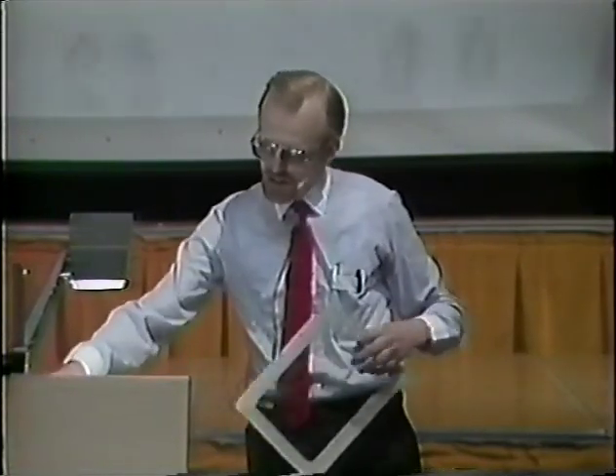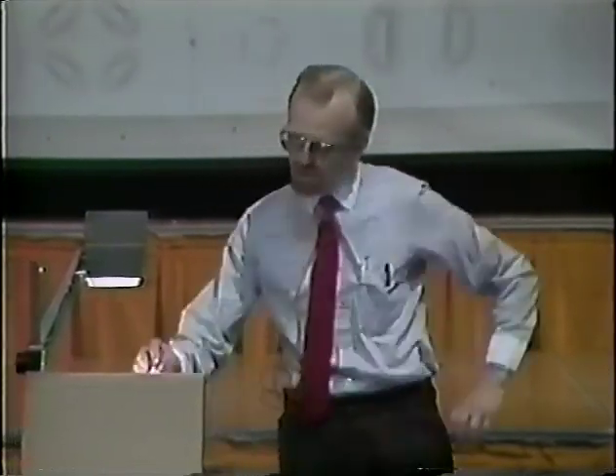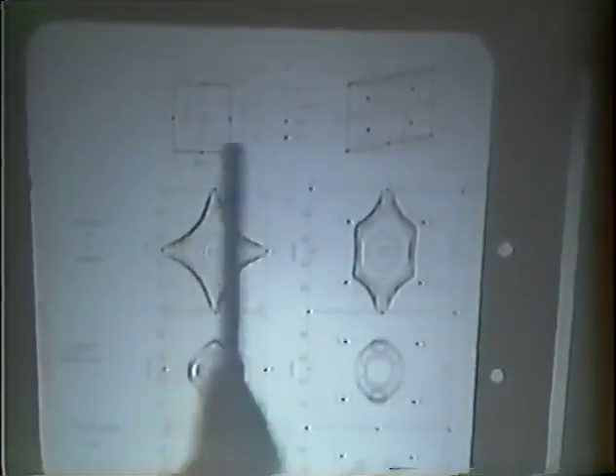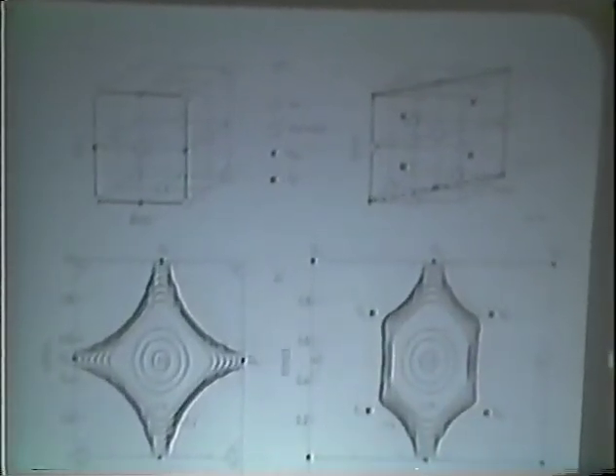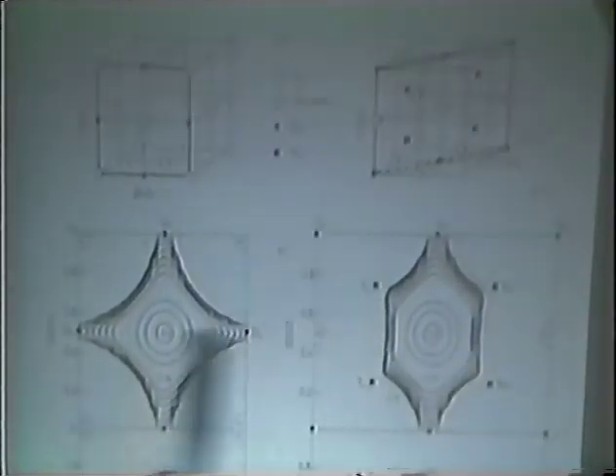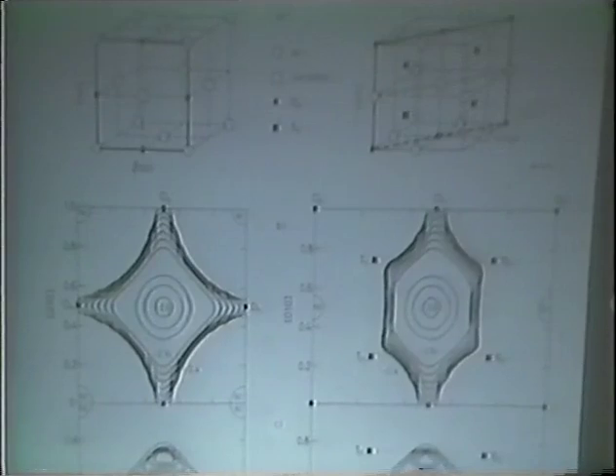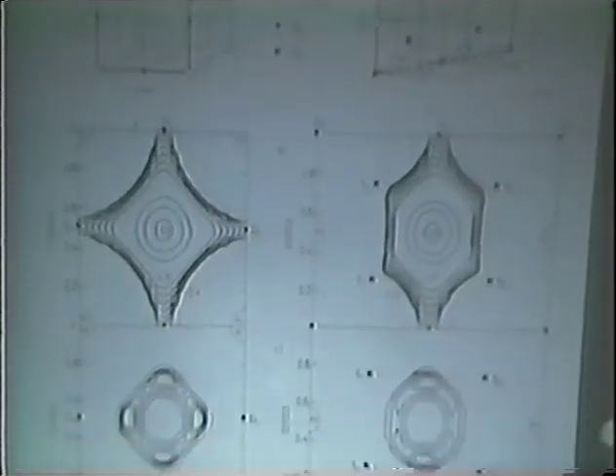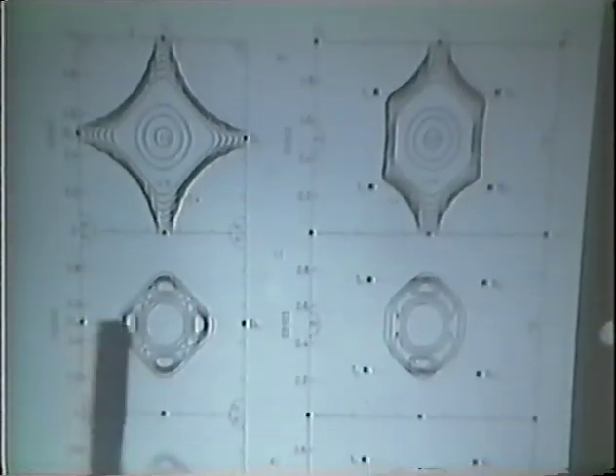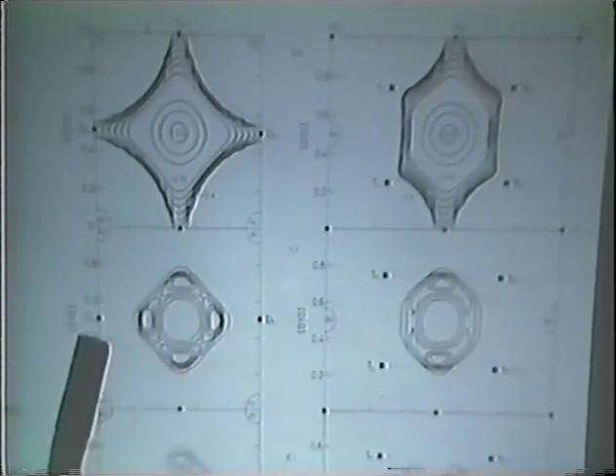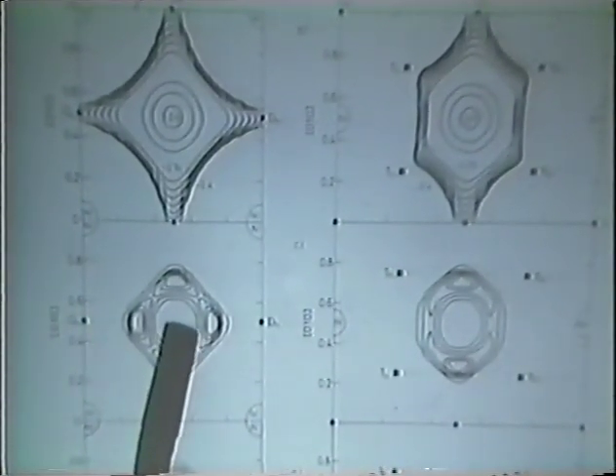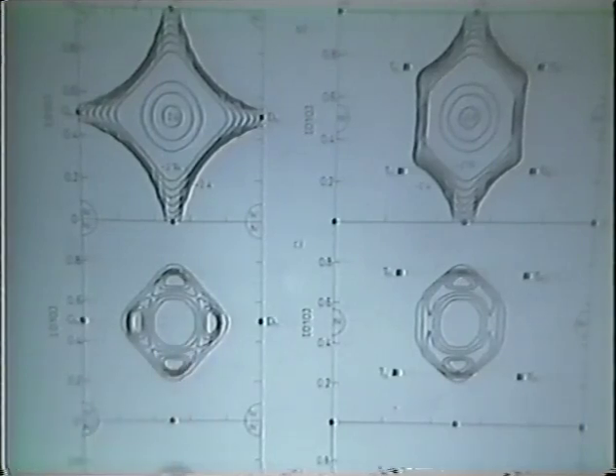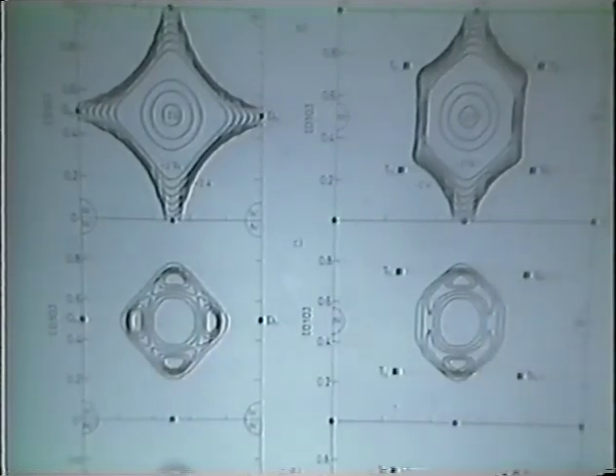If we now go back to the theory and see if we can understand that, I've here shown the potential from the theory along 2 different cuts along the crystal, one along the 100 plane and one along the 110 plane. And if you then take this potential, solve the Schrödinger equation, and get the wave function and the ground state density, we can see that there is in fact a maximum density for the site displaced away from the octahedral site towards the vacancy, which is sitting in the middle. However, we also had this tetrahedral component, which cannot be explained by the ground state.